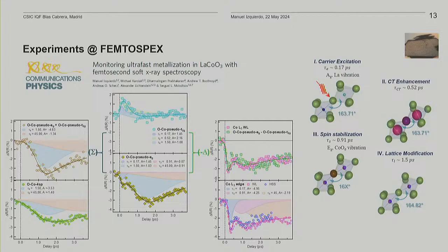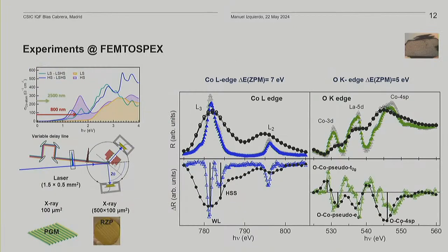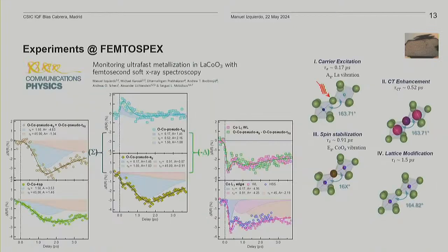So basically, what we did is we measured at resonant energies relevant to the T2G orbitals, to the EG orbitals, and to the cobalt 4sp band. This is for oxygen, and then in the region of the shoulder of the white line at the L3, where the high spin state of the system is supposed to show up.